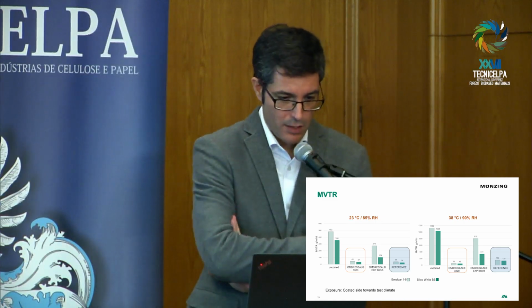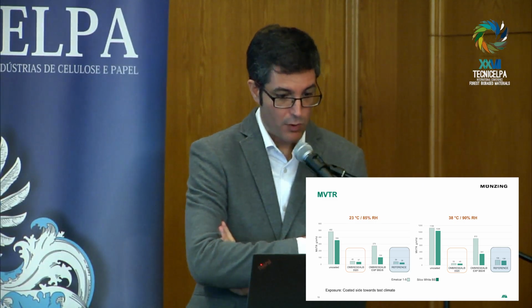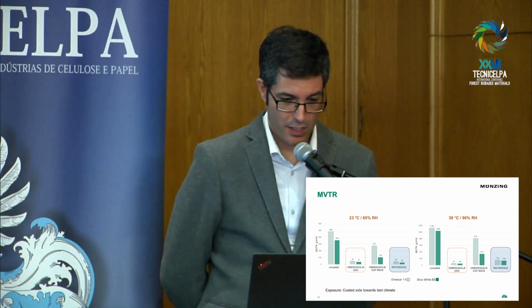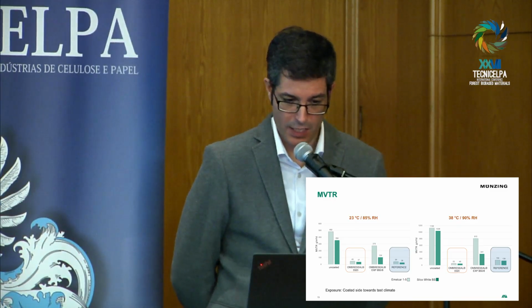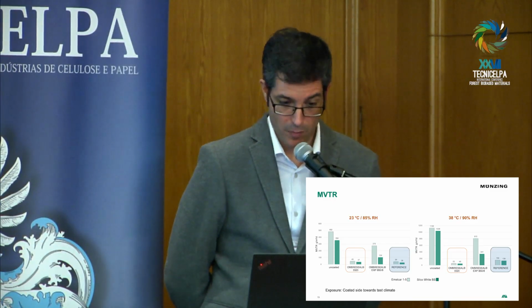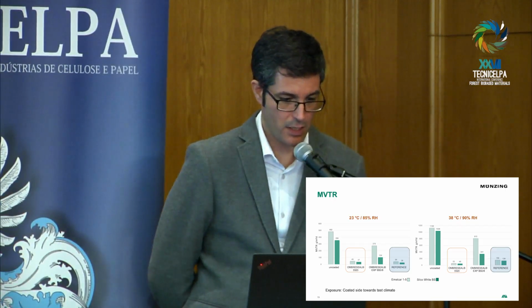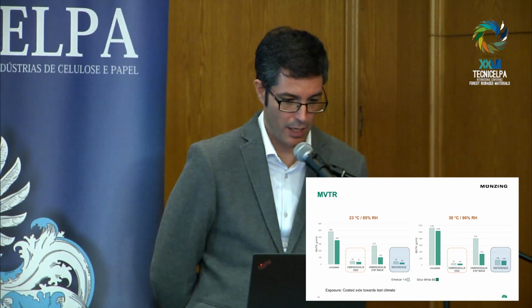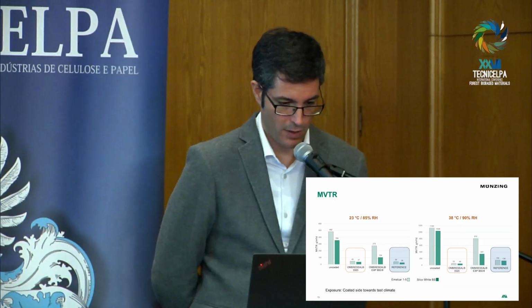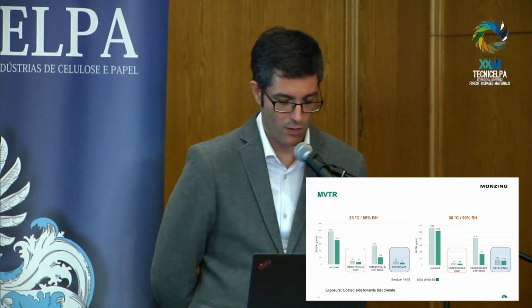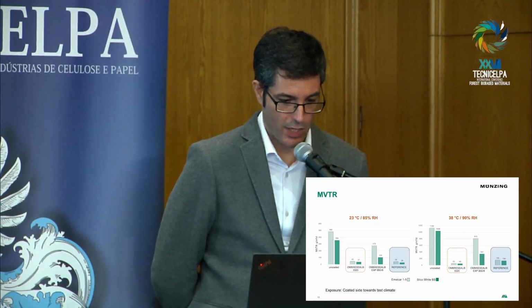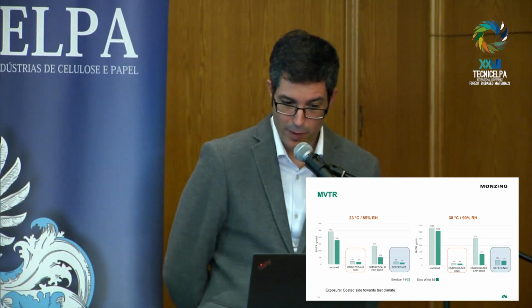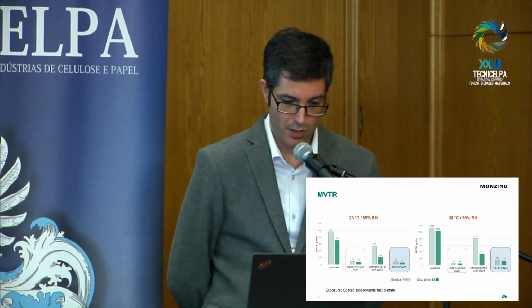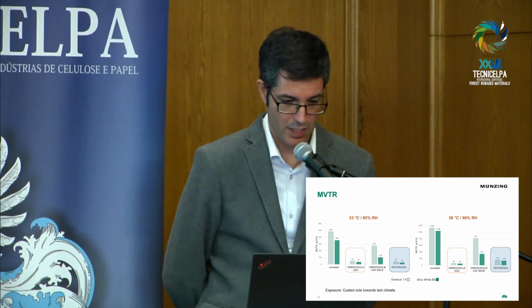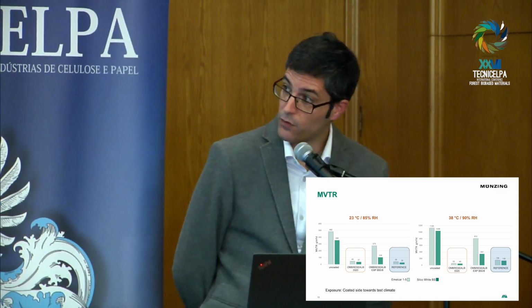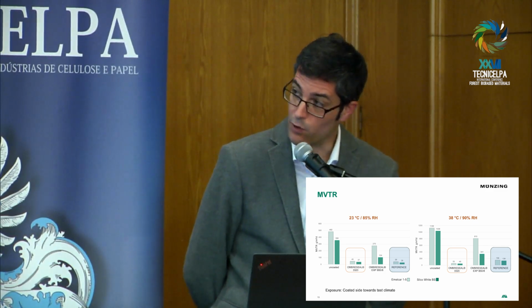So the first results we saw here are the moisture vapor transmission rate. As you can see, we test in two different conditions. On the left side is the standard conditions, on the right the tropical. It is clear that the uncoated, the non-pre-coated paper has higher absorption than the Silco White BS. And you can also see there is a significant improvement by adding the 6 grams per square meter of the XP B50/8. That can be enough for some applications, but maybe not for all of them.